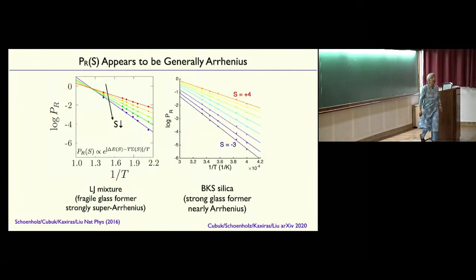So where is the e to the power N term coming from? If you were considering only a repulsive potential, then it will also depend upon the packing fraction of the system. If the packing fraction is low enough, then there will be a large number of minima as compared to e to the power N, right? Yeah, that's why it's order N. But we're considering high enough densities, which is where liquids are. Effectively, in terms of their repulsive cores, they're above jamming. They're very, very high.